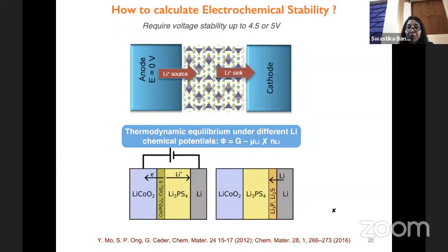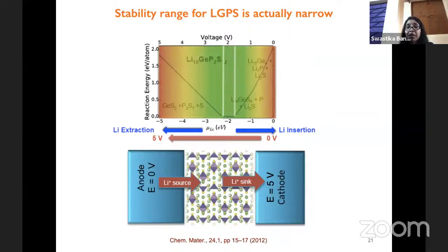For example, I have shown here the LiCoO2, LPS, and lithium. In this kind of setup, we have different products at the electrolyte interface beyond the limit of the stability window. So basically we have a limited potential to operate for such electrolytes. For example, for the LGPS I have shown here, if we construct the phase diagram in a similar way at different electrochemical potentials for lithium, we find that the potential window where the LGPS is stable is indeed very narrow. It is dictated by the other stable products which exist and can potentially be formed depending on thermodynamic criteria, so you cannot go beyond the limit. So it restricts the limit of operation for solid electrolytes.